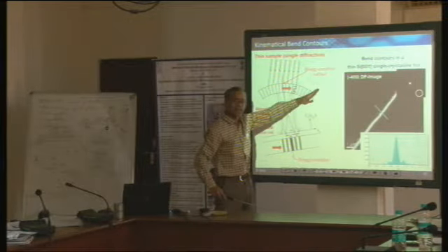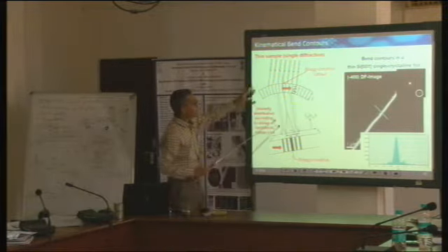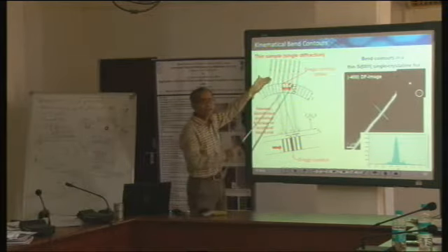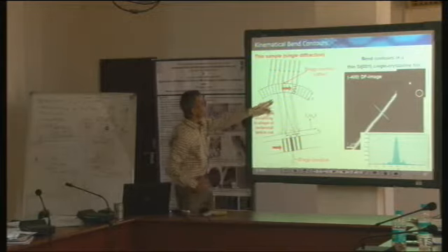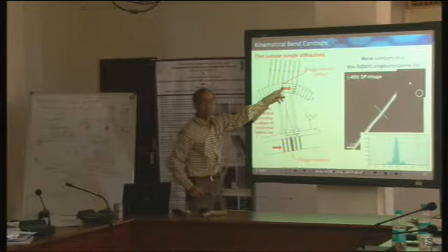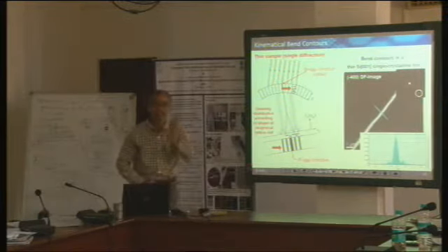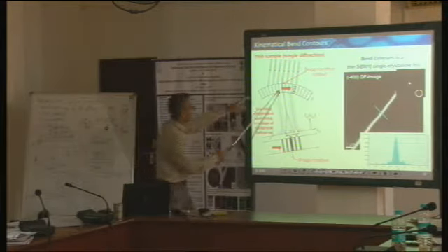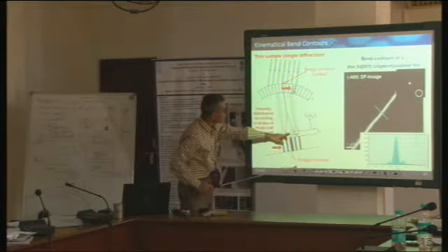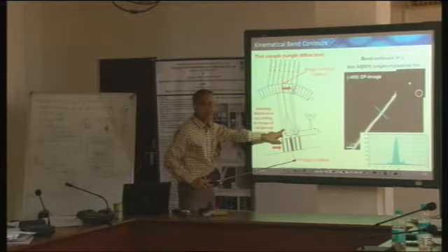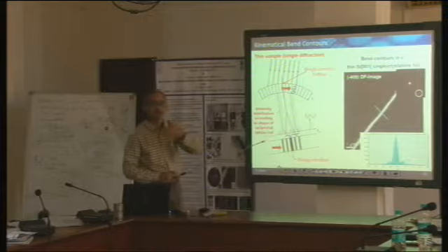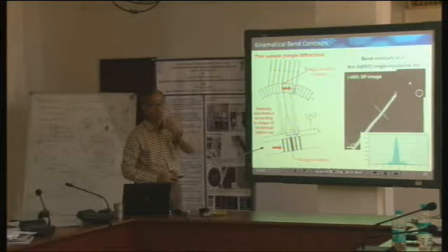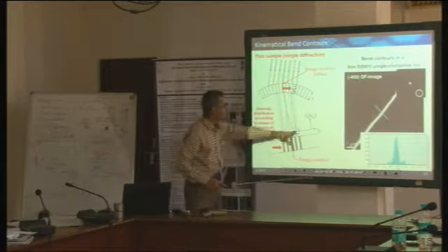Here it is in the other direction, and the incident beam is a parallel incident beam which has a fixed direction like this. Now let us make an assumption that at this particular point, the Bragg diffraction condition is exactly satisfied, which means that corresponding to these lattice planes, you get a maxima here. This is the same function which we have so far been knowing of, that kinematically derived equation, and it has been plotted here.